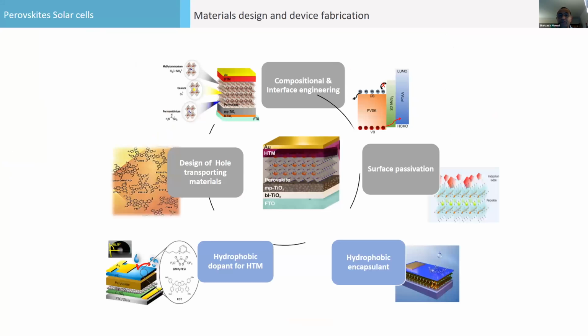My laboratory is working on all these phenomena and problems in perovskite solar cells. We do compositional and interface engineering. We change the composition of the active material, that is, the perovskite. We modify the interface by placing new materials there, which are energetically favorable, like 2D materials. Now we are thinking beyond graphene, the 2D materials here. For surface passivation, there are many modulators or passivating agents. We are using them to passivate the surface and fill the grain boundaries.